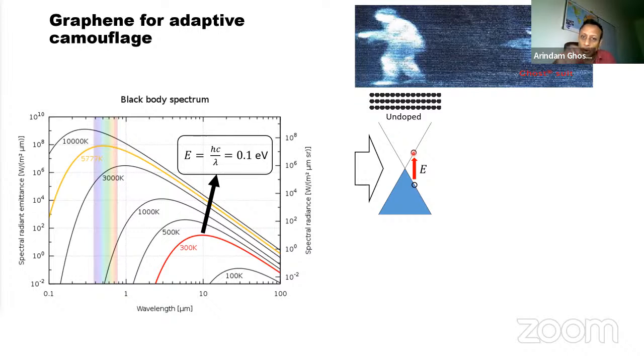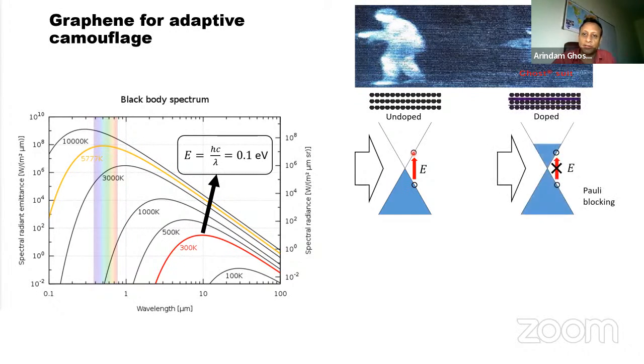However, if I dope the graphene the way I doped earlier, you saw the way electrons and holes were being doped using a gate. If I dope graphene such that there is no available state at these energies of few hundred milli-electron volt or so, then a charge from here cannot get transferred to a filled state through a phenomenon called Pauli blocking, and hence the energy that was coming can no longer get absorbed, and if they cannot get absorbed, they cannot get emitted either. And this is how a ghost suit can be created.